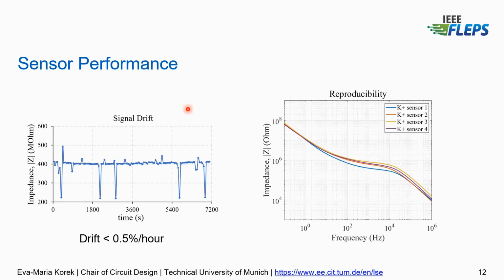We also checked the sensor drift, and the sensor has very low drift. If we look at this value, it's less than 0.5% per hour, and this is even lower than the resolution of our measurement device. So it might also be due to the measurement device. And these peaks, actually, they stem from environmental noise because we're measuring such high impedances. We catch a lot of environmental noises.